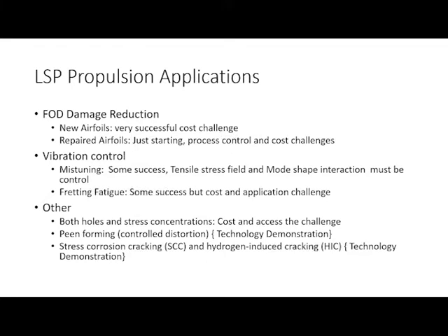The success of them has been phenomenal. I'm trying to remember, but I think we've only failed 1 or 2 airfoils, and we've got hundreds of thousands of airfoils that have been LSP'd and gone through a lifetime. So the success of the LSP application to airfoils is overwhelming.